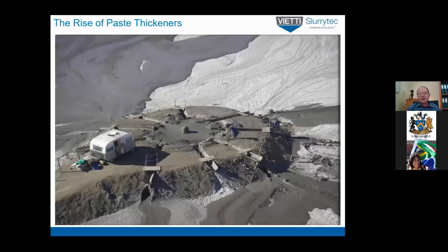And again, a very clever geotechnical engineer came up with this system, which is a unique South African design, which he calls the wagon wheel. The idea here was to be able to distribute that tailings around that point of discharge, because previously the material would just flow wherever it felt like. What he did was take advantage of what's called the plunge pool. There's a pipeline that runs underneath this ramp, and it elbows up here, and it basically open ends there, and the tailings flow out like a chocolate fountain in a way. It was quite nice. And it forms a plunge pool. And then he put spokes on this plunge pool with these half pipes, and these half pipes were then blocked with sandbags, and he would then lift that, and it would allow the flow to go in whatever direction he wanted.